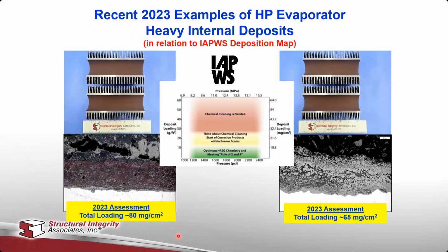So the second area is to make sure that you have the right level of deposits on the internal surfaces of the HP evaporator. And again, this is from the IAPWS guidance document for those deposits. Again, it's freely available, and you have up the vertical axis the deposit loading on the internal surface in grams per foot squared or milligrams per centimeter squared. As a function of pressure, where you want to be is in this green area right here.